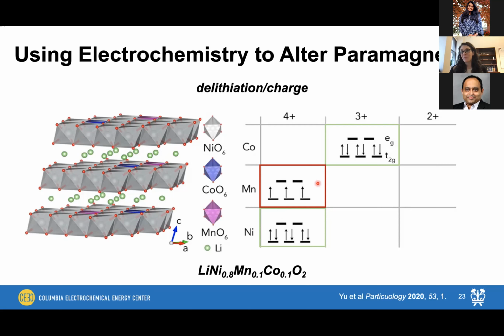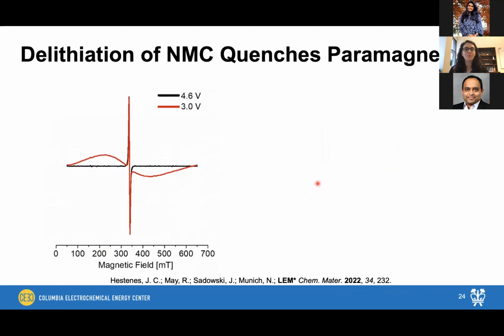First with EPR, where our EPR signal should be directly proportional to the number of unpaired electrons that we actually have in our system. So what you're looking at here is the EPR spectrum for the battery in the discharge state in red. So what you see here is this very broad signal here. This comes from the NMC811 particles. And then we have this sharp signal in the center. This comes from our conductive carbon additive. So there's also some delocalized electrons on the conductive carbon.